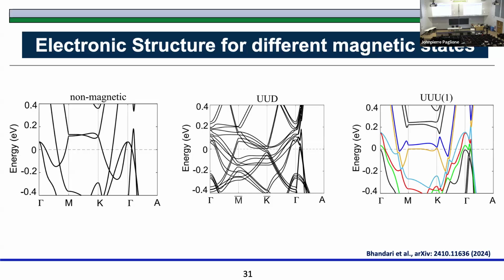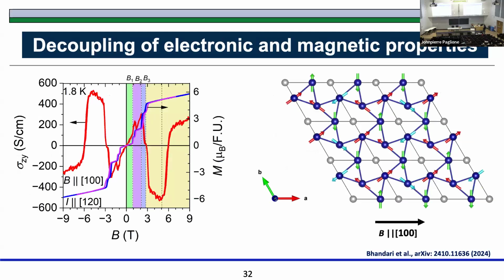And because now it has a magnetism, the bands split here, and it brings these flat bands and the Dirac point right at the Fermi energy. Okay? It is not only the change in the Fermi surface topology, but tuning these interesting features right at the Fermi energy. And that may have some effect on the electronic structure. And more than that, what we found, this is only some hand-waving argument. Some amazing thing happened in this material.